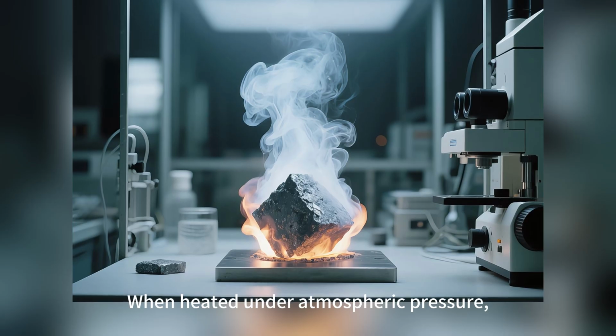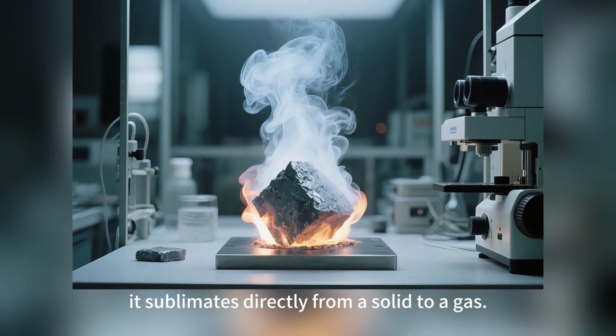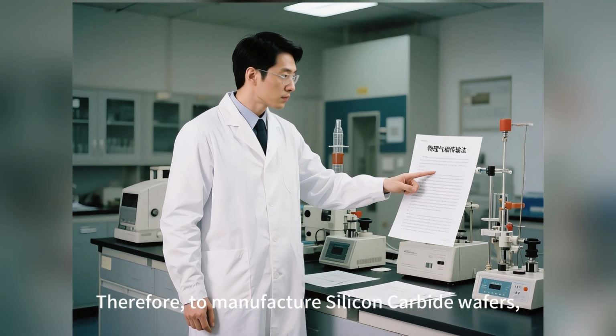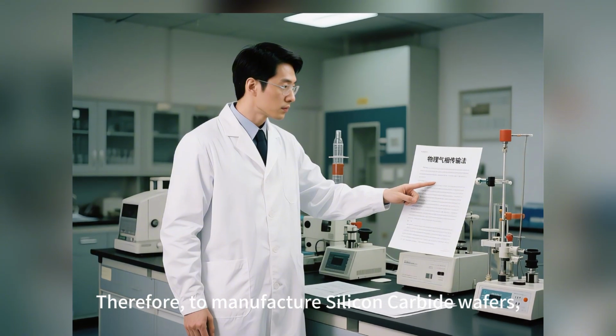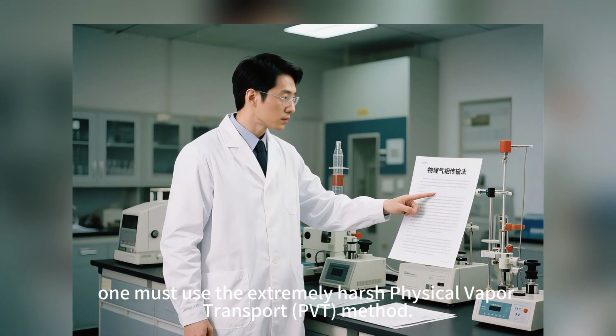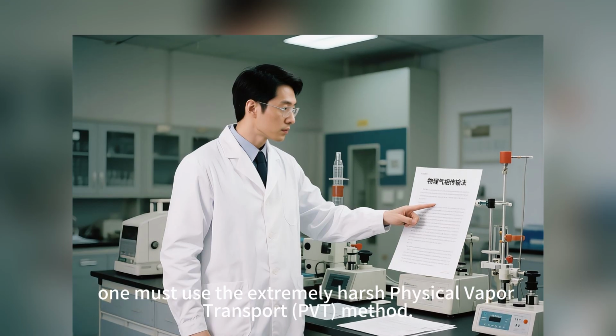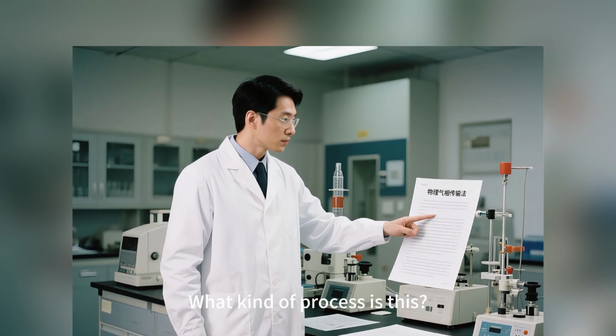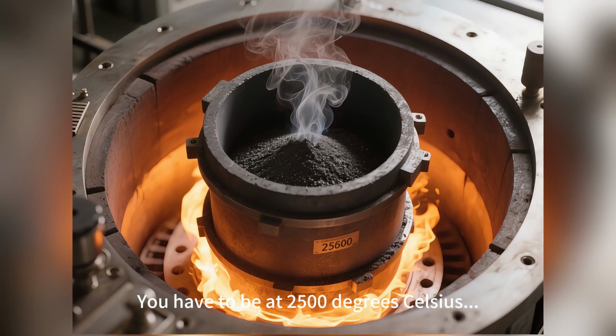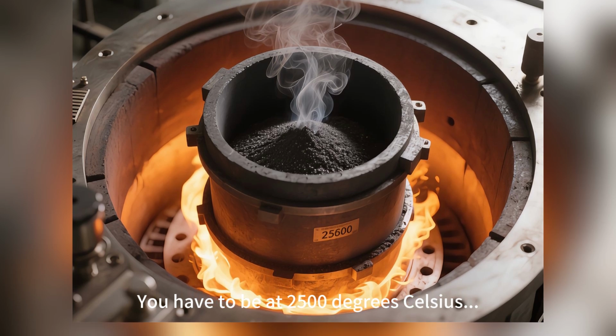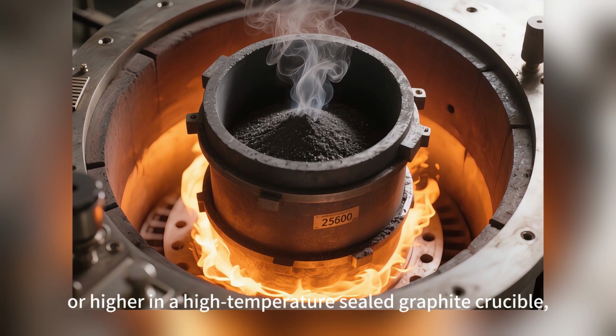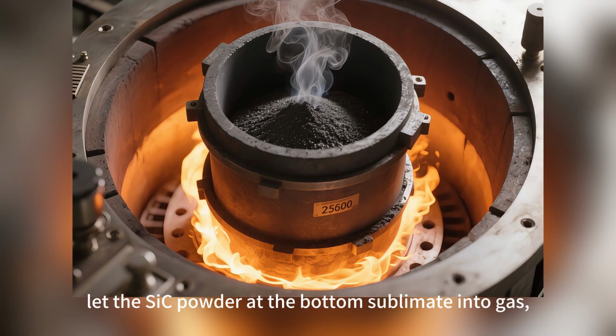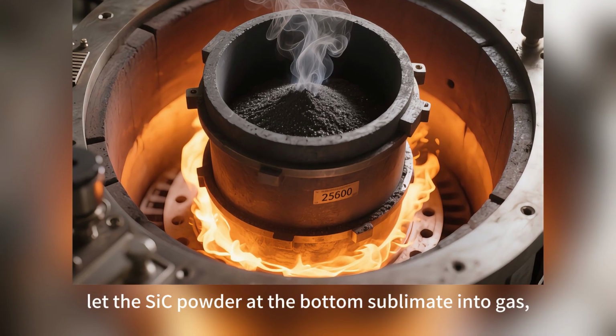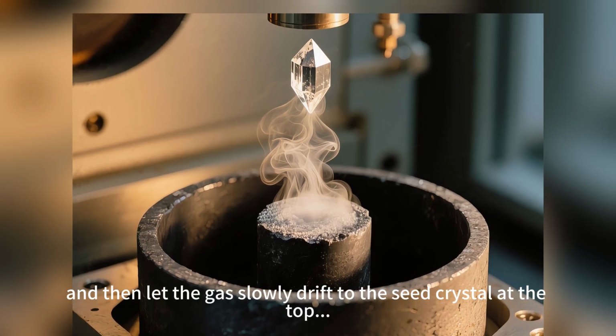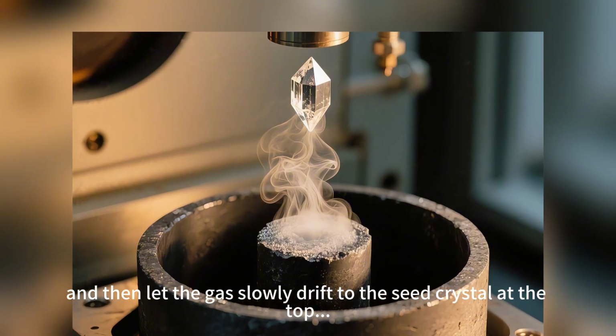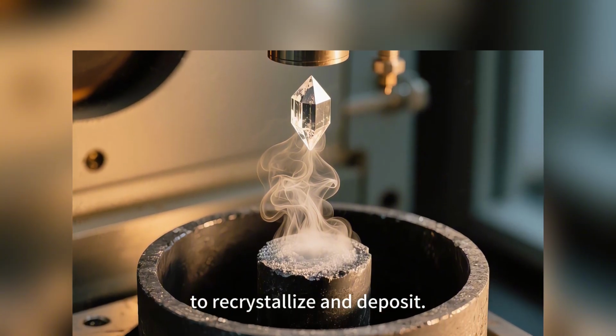When heated under atmospheric pressure, it sublimates directly from a solid to a gas. Therefore, to manufacture silicon carbide wafers, one must use the extremely harsh physical vapor transport PVT method. What kind of process is this? You have to be at 2,500 degrees Celsius or higher in a high-temperature sealed graphite crucible. Let the SiC powder at the bottom sublimate into gas, and then let the gas slowly drift to the seed crystal at the top to recrystallize and deposit.